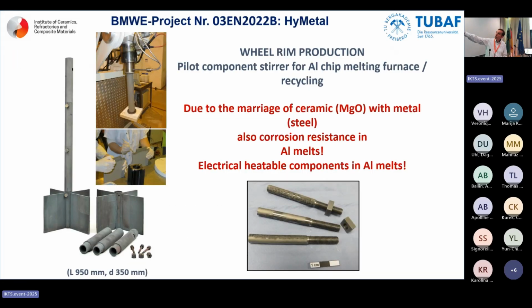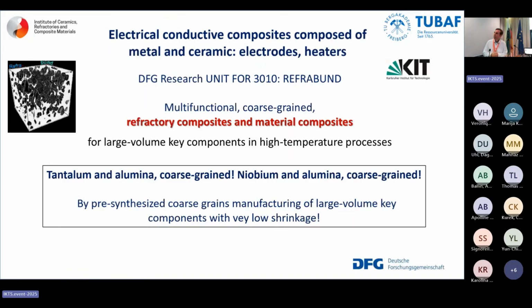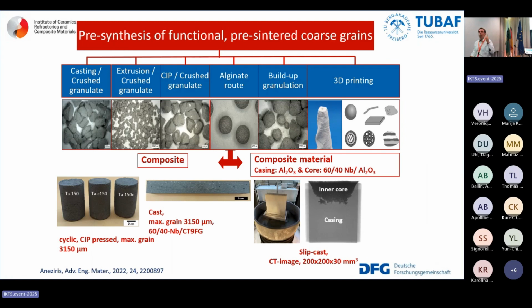Or you can make screws and all these kind of things. It's the ceramic technology applied to a metal ceramic composite system. And these are preheatable electric conductive systems, not for steel applications, but for aluminum. And of course, because we had John before, let's go to a marriage between refractory composites and material composites, in means of getting refractory metals, tantalum and niobium, and putting them with alumina. Somebody would say, yes, this is well known. Yes, it's well known, but let's add one more puzzle piece.